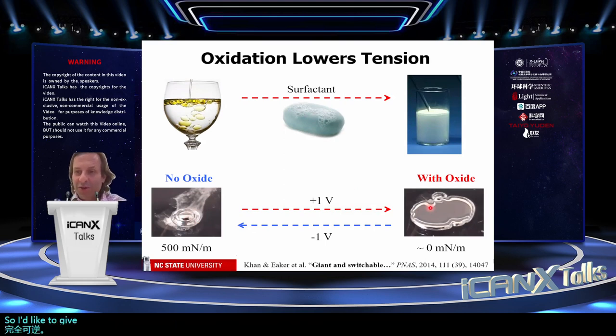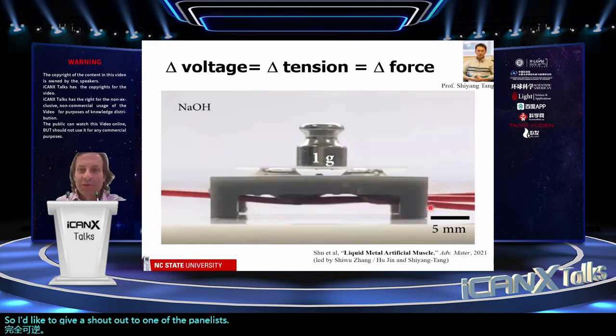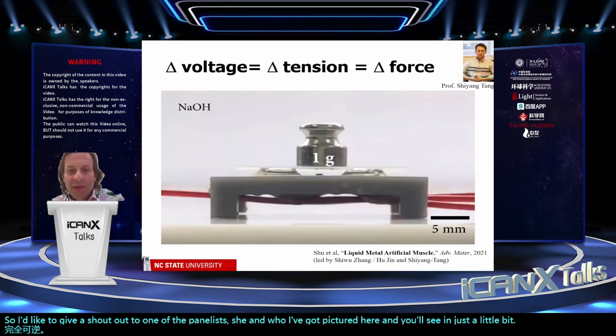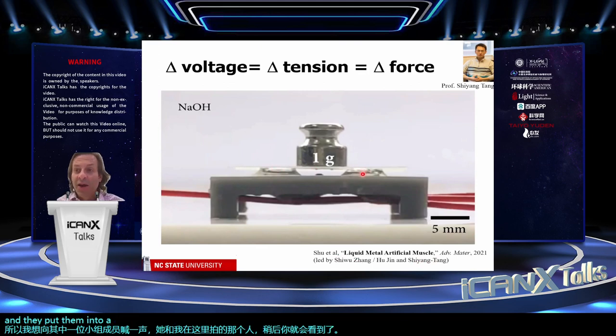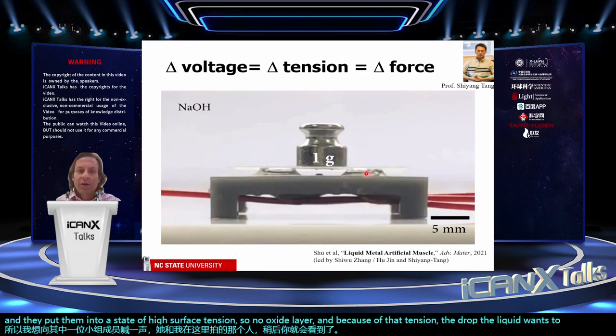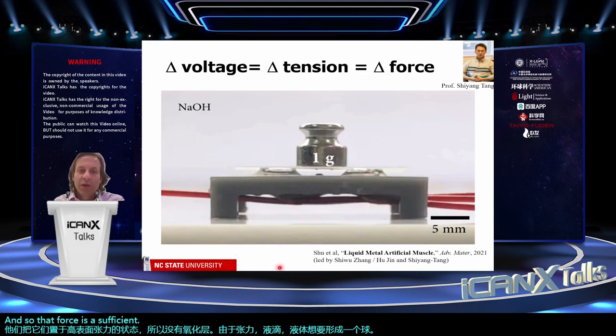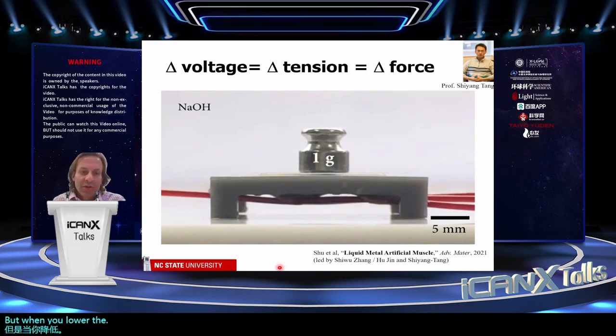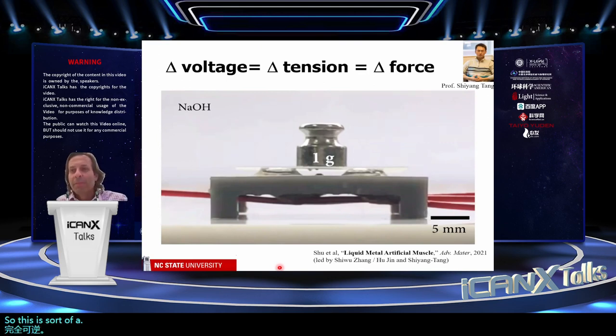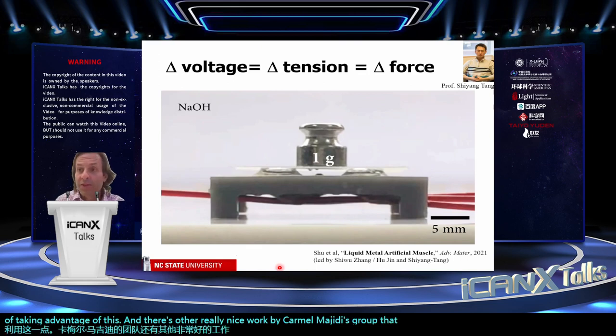So I'd like to give a shout out to one of the panelists, Shiyang, who I've got pictured here, and you'll see in just a little bit. He and some collaborators did this really beautiful work where they took liquid metal droplets and they put them into a state of high surface tension, so no oxide layer. And because of that tension, the liquid wants to form a ball. And so that force is sufficient to hold up this weight. But when you lower the surface tension by applying voltage, the weight squishes it down and then it's completely reversible. So this is sort of a muscle-like material in which the force is coming from the surface tension. So this is really a beautiful example of taking advantage of this. And there's other really nice work by Carmel Majidi's group that does similar things.